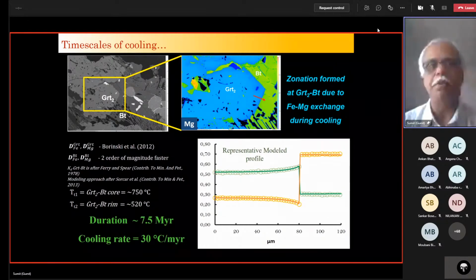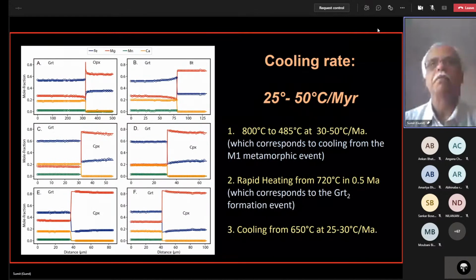Now, what does that tell you? It tells you that this cooling from 750 to 520 degrees happened in 7.5 million years. And the cooling rate was about 30 degrees centigrade per million years. Okay? So you can do this with all the other minerals. I completely did this for all the other minerals.